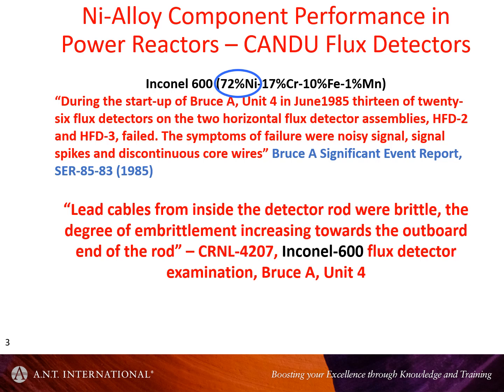And it turns out that, many years ago, flux detectors were exposed to the moisture from the vault, and they realized that this was bad because you'd get nitric acid being produced with all the gamma radiation around, and early flux detectors in CANDU reactor designs were failing because of nitric acid attack. So then they encapsulated them in helium-filled tubes that went right through the reactor. But even then, after about 5 or 6 years, they would break, during startup, and ostensibly you could just replace them. But just by routine, there'd be a bit of a surveillance examination just to make sure it was nothing unusual. But it was unusual. These things were very brittle, and you couldn't attribute it to nitric acid attack. So that was my first introduction to the peculiarities of Inconel components.